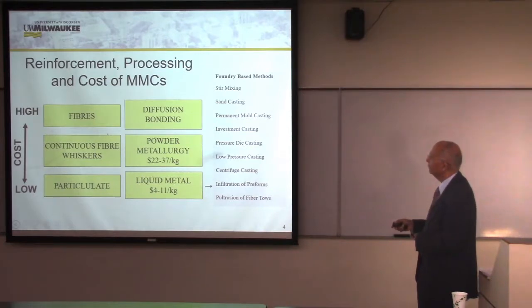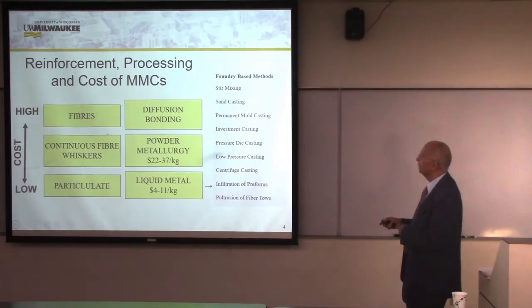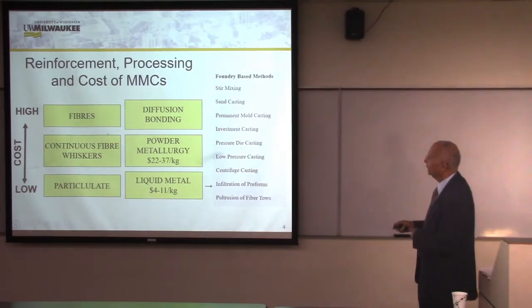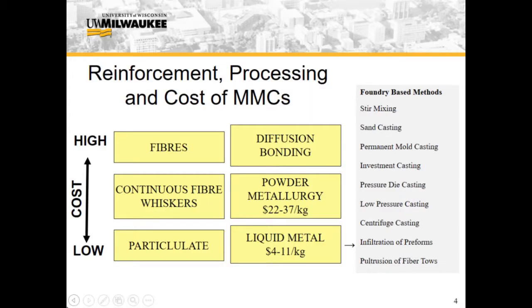The methods by which you can mix the reinforcement and the matrix can be three types. One is that you can use diffusion bonding, where you put layers of one phase, and in the middle you put fibers, you press them and consolidate them by diffusion bonding. The other is by powder methods. You take a mixture of metal powder and ceramic particle powder, press them, and that produces a metal matrix composite. The third method, which is the foundry based method, is where you melt liquid metal and add the particulates or even fibers to that and allow the liquid to solidify to produce metal matrix composites.